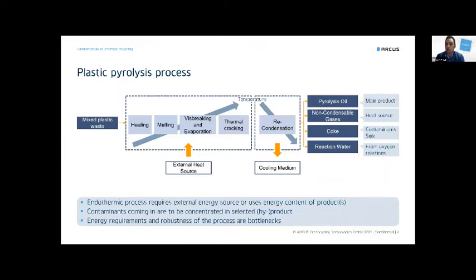And then finally you will have thermal cracking where the larger polymers become smaller and smaller, and there you might have your monomers like ethylene, propylene, but also a wild mix of hydrocarbons from C5 up to larger waxes. So that's the heating part of a pyrolysis process. And then in the second part, you need a cooling medium to reconvert the vapors you produce during pyrolysis into a liquid. And this liquid, which we call pyrolysis oil, is the main product of this kind of process.